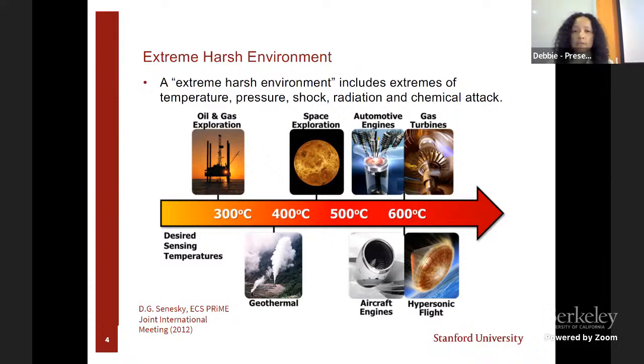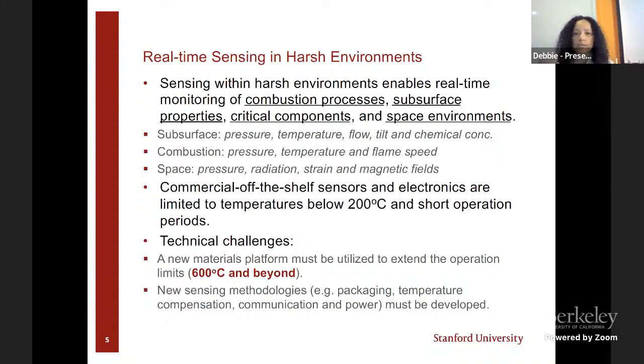And again, the ability to collect data about combustion processes, subsurface properties, critical components, space environments. And then we would be really stressing our electronics, and the idea of being able to stress these electronics and still collect very, very important information. And again, our traditional silicon-based electronics cannot function above 200 degrees Celsius. You can push that up to slightly higher temperatures using a silicon on insulator process. But at these temperatures, you're going to start to generate thermal carriers that dominate the electrical properties. And so it's difficult to transduce within those kinds of temperatures.